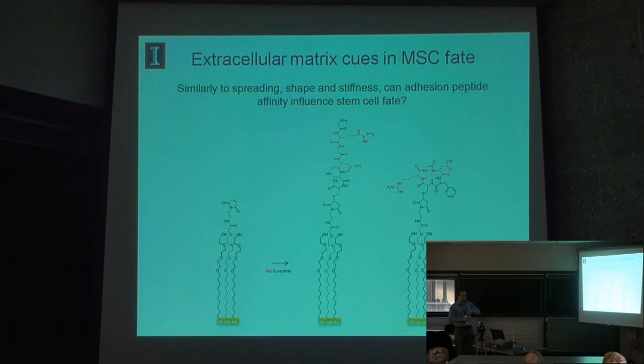And so to do that, we used our self-assembled monolayer chemistry, but this time using this maleimide functionalized monomer that we mixed into the SAM, and then we immobilized a thiolated peptide. One which has the RGD peptide, shown here in red, which is the linear peptide that's utilized in most biomaterials proof of principle studies. We also used the cyclic analog that had been explored for years as a therapeutic candidate.